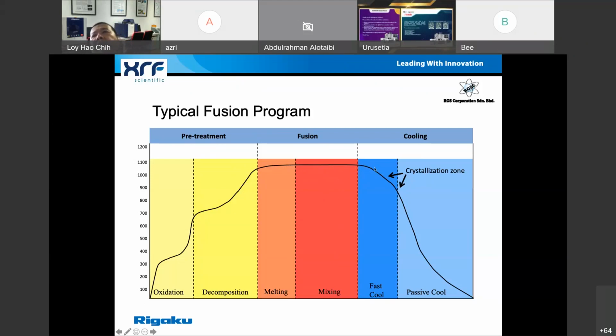When you pour it out, it goes through a very fast cooling process. This is to ensure that crystallization can't happen, so the flux can set the sample into a very nice and clean bead. Once it's done, we passively cool it so that we can take it out of the platinum mold at a later stage.